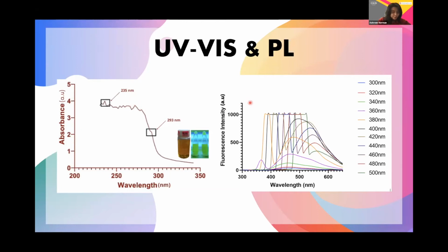So the photoluminescent result also shows that it is an excitation-dependent PL feature. Something spectacular actually happens when the CDs are excited at 380 nm and beyond. Twin peaks occur in the range of 380 nm to 500 nm, followed by an emission peak at 490 nm when excited at 400 nm. The emission peaks begin to decline beyond the excitation of 500 nm.